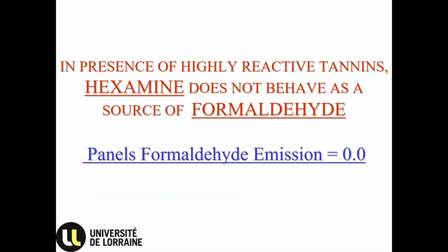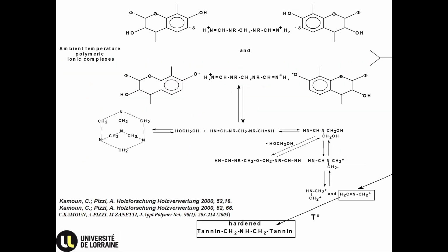In the presence of highly reactive tannins, hexamine, the famous hexamine, does not behave as a source of formaldehyde. Formaldehyde emission equals 0.0. It is a trick, fundamentally, but it works very nicely. And that you can actually see.